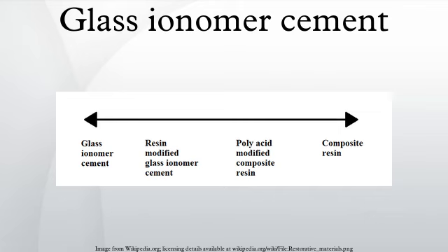Biocompatibility. The biocompatibility of glass ionomer cements is very important because they need to be in direct contact with enamel and dentin if any chemical adhesion is to occur. In an in vitro study, freshly mixed conventional glass ionomer cement was found to be cytotoxic, but the set cement had no effect on cell cultures.